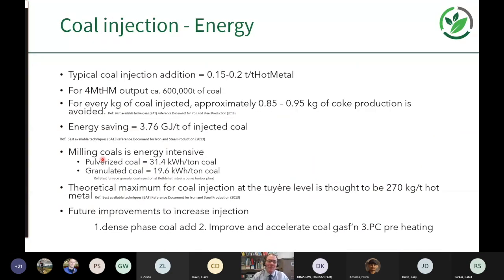But in terms of energy, typically the coal injection additions would be up to a couple of hundred kilograms per ton of hot metal. So for an output of 4 million tons, which would be typical of Port Talbot, we're talking about 600,000 tons of coal. And you substitute that for about 0.85 to 0.95 kilograms of coke per kilogram of coal. So you avoid that coke production, and you reduce the emissions associated with it. And there's a significant energy saving. Best available technique data quantifies that at 3.76 gigajoules per ton of injected coal. So there's an energy saving associated with it.